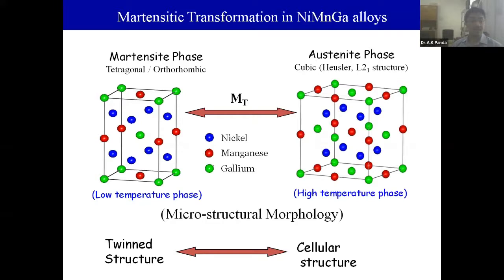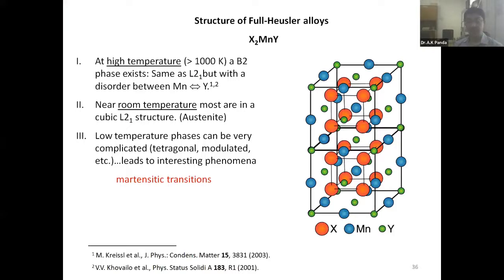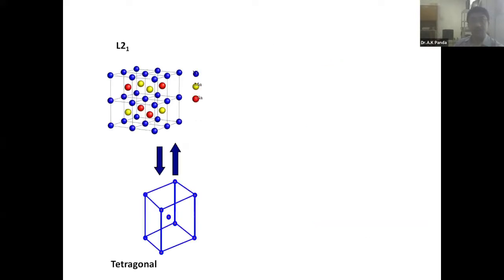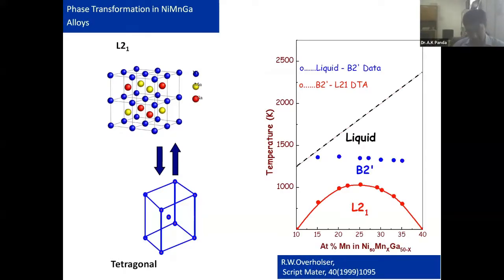The symmetry is quite different. There's a lot of asymmetry, a lot of strain in it. So I go further. This is the full Heusler system that typically looks like this, with a high temperature B2 phase and low temperature L21. The low temperature martensite is still below the austenite, and that is tetragonal, and even the modulated, even the non-modulated ones. So this is how it looks when you go down. It is tetragonal, and this is typically a phase diagram that tells you what it looks like. You have a liquidus level, and a B2 prime and L21, which I told you is just interpenetrating cubic lattices.